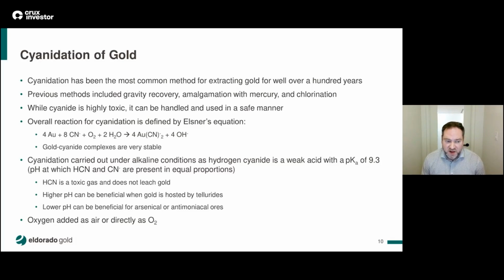It's also important that we carry out the leaching under alkaline conditions, as HCN can be formed below pHs of typically around 9.3. And HCN is a toxic gas, and it also does not leach gold. So the cyanide is not in a useful form if the pH is too low. We typically run at a high pH, and higher pHs can be beneficial if there's gold hosted in telluride minerals, and slightly lower pH if we're looking at minerals that contain arsenic or antimony. Oxygen is added as air or directly as oxygen.